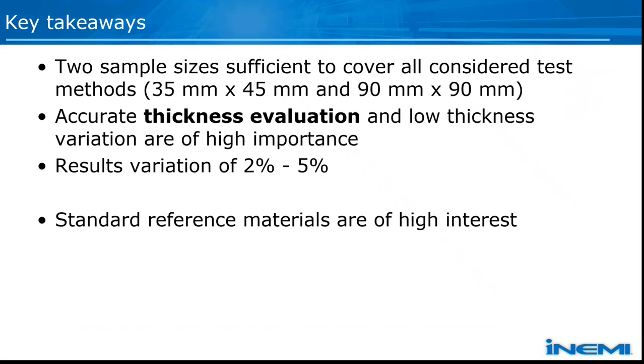So our key takeaways really sort of mirror those of task 3, thankfully. So the key two, in my opinion, are that with just 2 different sample sizes, the 35 by 45 millimeter samples and the 90 by 90 squares, we're able to sufficiently measure all of these materials with all 4 of our techniques of interest, the SPDR, SCR, BCDR, and FPOR. Additionally, like Mike just highlighted, we really found that the thickness evaluation and thickness variation within a sample were both huge indicators of the kind of variation we could expect out of measurements on a given sample.